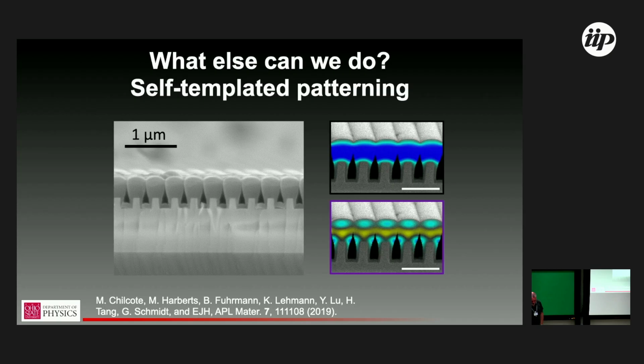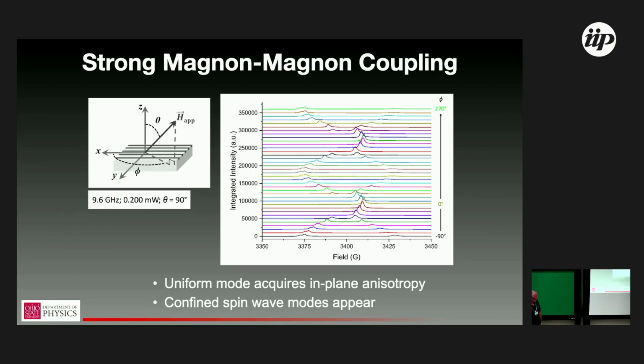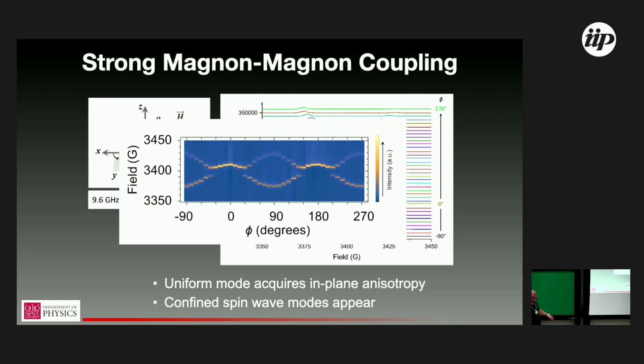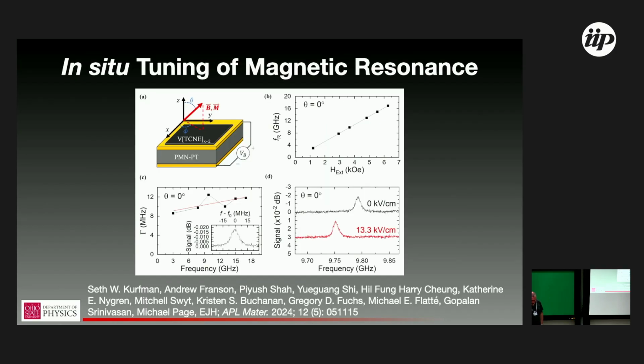So I have 10 minutes left, so I'm just gonna quickly throw these up. We can circle back. I'll try and leave as much time for questions, but we can do self-templated patterning, again using Mumax for the color contrast to show the spin wave spectra. If we do the angle-dependent FMR, we can vary the coupling between different magnon modes within that complex structure, and in fact can see very clear anti-crossing between magnon modes. So I'll call this the strong magnon-magnon coupling regime. That's a fun place to engineer and look for new problems.